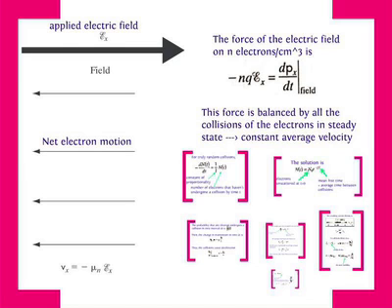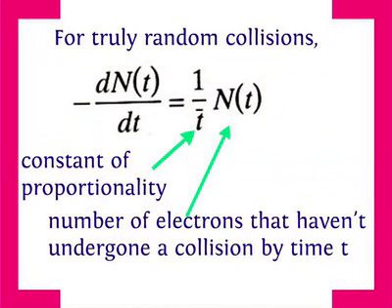What happens, of course, is that there is an effective deceleration that happens as the electrons collide with the crystal vibrations and so on. So this acceleration in the field is balanced by collisions in the crystal and other collisions, electron-electron collisions, electron-defect collisions, and so on. So we have to do the other force, which is the decelerating force calculation. Okay, that's the next step. That's a bit more complicated. It involves statistics of random processes. Okay, because the electrons collide randomly with everything else.